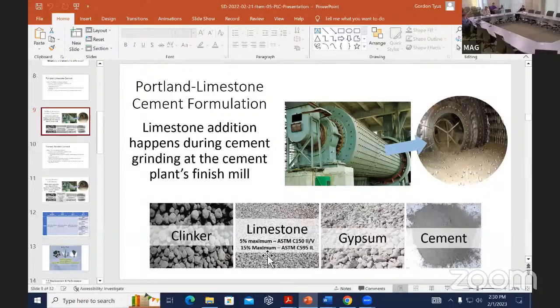At 4-5% limestone, you get actual strength gain. You have more strength gain than you do without limestone. And then when you start taking that out, the opposite is with the porosity. And they cross with the strength. The limestone goes up to about 12.5, 13, and I've got to pull that graph up. But it's basically where they intersect. 15 was the sweet spot where you have the most dense, least permeable concrete, and then that's right when the limestone starts to directly hurt the strength. But they do have 20s and 30s and 40% limestones in Europe. But we stayed at 15.